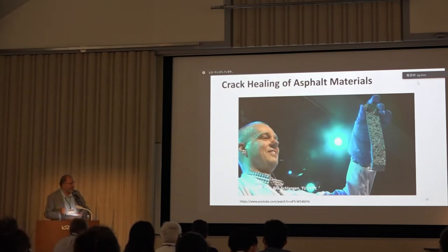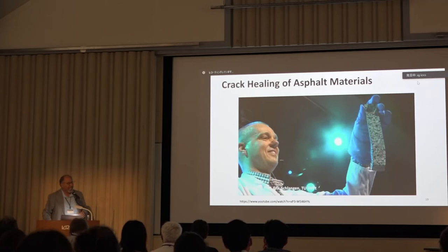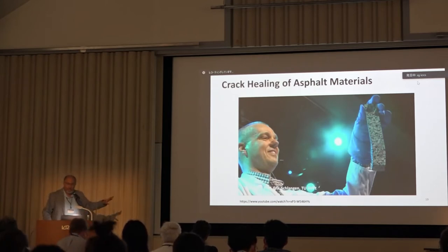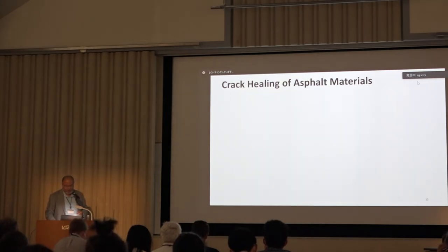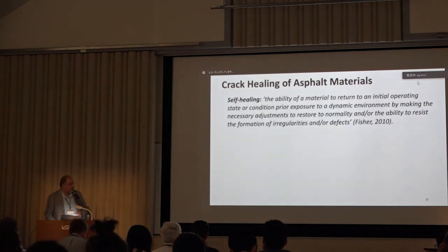Like, it's a problem, right? So this is why I never use any demos like this. But it was successful, and the crack healed, actually. He demonstrated that we can heal cracks in the asphalt by putting together the two parts and increasing the temperature in the microwave. We don't use microwave in real life, we use induction. This is another solution. But that was one of the videos and the early works on asphalt.